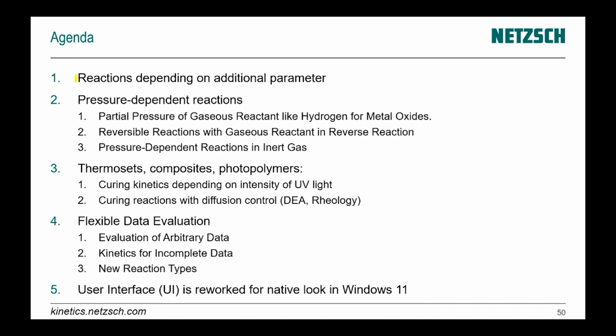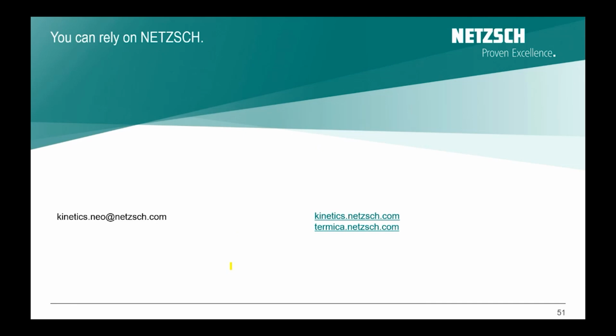We have now reactions depending on additional parameters, for example, pressure dependence reactions with a gaseous reactant like hydrogen, with a gaseous reactant for a reverse reaction in reversible reactions. We have pressure dependence reactions in inert gas. We can use intensity of UV light as a second parameter for photopolymers. We have curing reactions with diffusion control for DEA and rheology data, for example, for shear viscosity. We have flexible data evaluation with new arbitrary data types, incomplete data, new reaction types and a new user interface. That's all from my side.